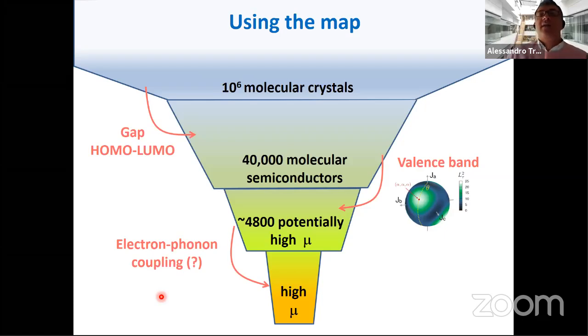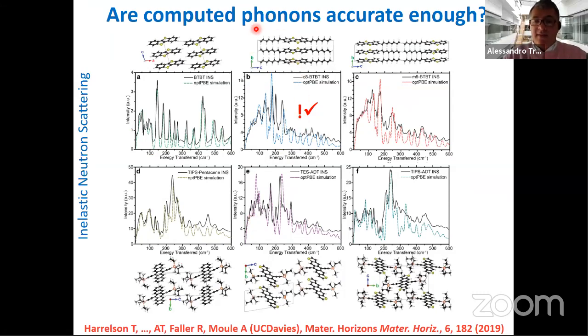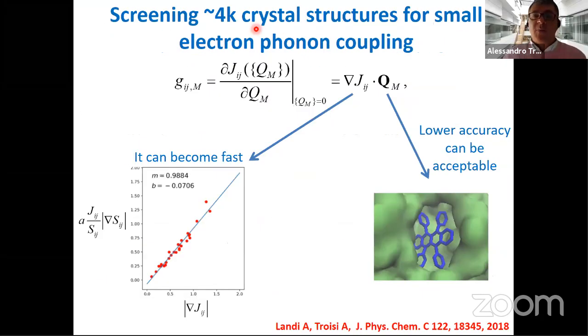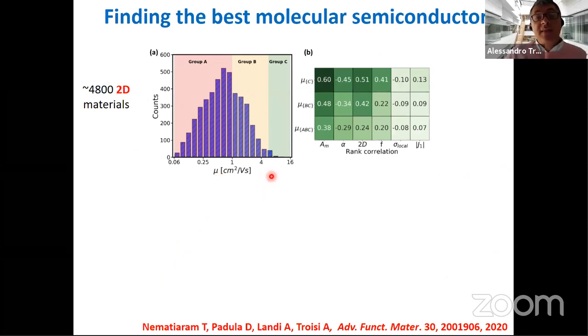So what we did, and I'll go quick because I'm running out of time, was to develop an accelerated methodology to compute the electron phonon coupling for up to 5,000, or this order of magnitude, of molecules. We checked, well, I'll skip this. We have a very good way of computing it accurately. So the problem was to compute it approximately. So we created an approximation where a molecule is surrounded by rigid molecules, which are described only classically. Essentially, we use the QM/MM approach to describe the phonon of the molecule. We validated it. And so we concluded with the computation of the predicted mobility of the most promising 4,000 materials.